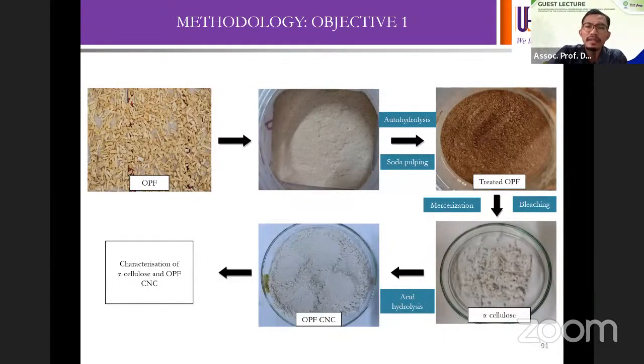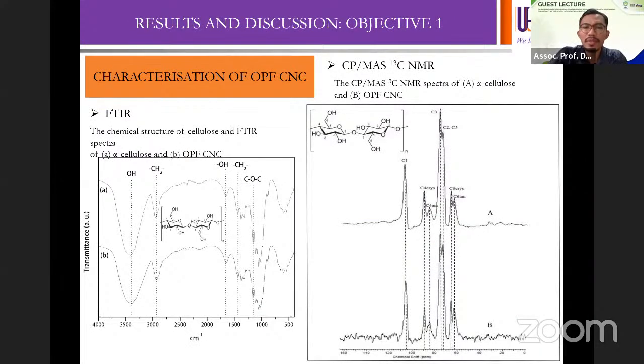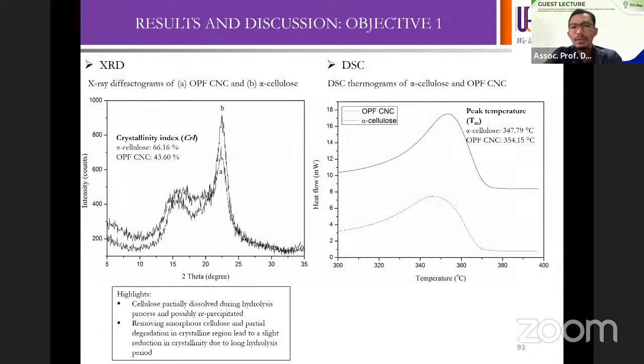Of course, in order to isolate the cellulose, we need to do a pulping process, and after the pulping process, we need to bleach the pulp, and it forms the alpha cellulose, which we subject to acid hydrolysis to form cellulose nanocrystal samples. The cellulose nanocrystal sample is subjected to different characterization. You can see from the FTIR, mostly cellulose, and we also did solid state NMR to check the crystallinity of the cellulose produced. You can see that the C4 and C6 of the cellulose structure, especially the crystal peaks, are even greater than the amorphous peak. We also quantified the crystallinity index and the melting temperature of the nanocellulose that we have produced.